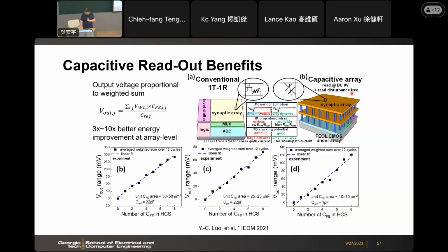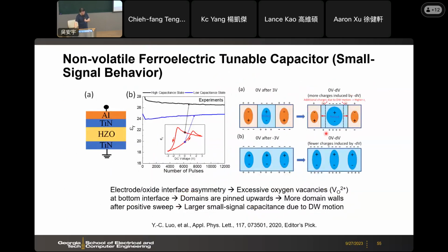Okay, good point. So we measured from the normal, let's say, integrated semiconductor parameter analyzer. The CV unit built in, you can measure up to 10 megahertz. And we measured up to 10 megahertz. The behavior is like this. And then we also, I didn't quote the paper here, had an RF test structure where we have the GSG probe with RF testing. We measured up to, I believe, 2 gigahertz. The window shrinks at higher frequency, and you still have some dispersion. But still, the trend is there.